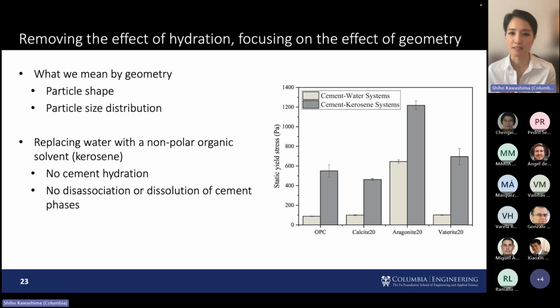So what I'm going to present is we looked at the effect of geometry, and then we also looked at the effect of hydration. So what do we mean by geometry? So here we're focusing on the effect of geometry. And by geometry, I mean the particle shape and the particle size distribution. And so just remember those SEM images of all the different polymorphs. They're very different, right? In particular, the aragonite is very different. They're needle-like.